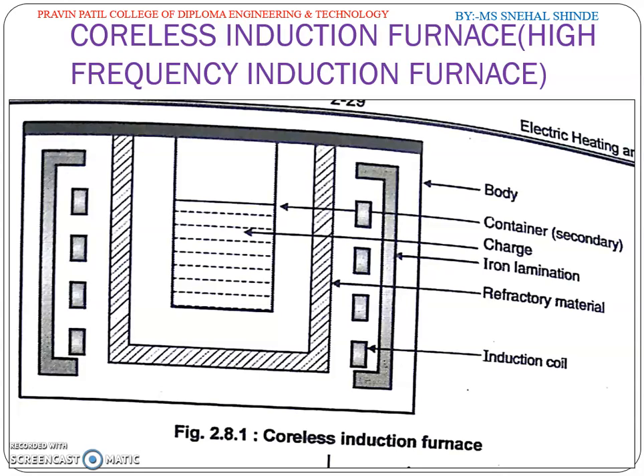Heat in the charge is produced by eddy currents flowing concentrically. High frequency supply is preferred, 500 to 1000 Hz, because eddy current is proportional to B square F square. With this method, it is possible to employ vacuum heating required for heating precious materials. Power factor of this furnace is very low and efficiency is very low.